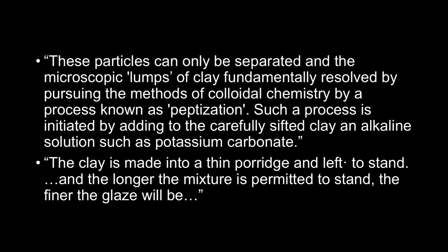It is now established that no pigment was needed, but that the color differentiation was produced entirely by the action of firing on the clay. The Greeks subjected the vases decorated by means of the gluey colloid first to an oxidizing fire, thereupon to a reducing fire, and finally left them to cool down under oxidizing conditions. With that, Schumann finally completed a 200-year-long process to understand these ancient finishes. However, what he didn't explain is how artists would use these ideas today. And my colleague, Rhonda Willers, is here to explain that half of the story.